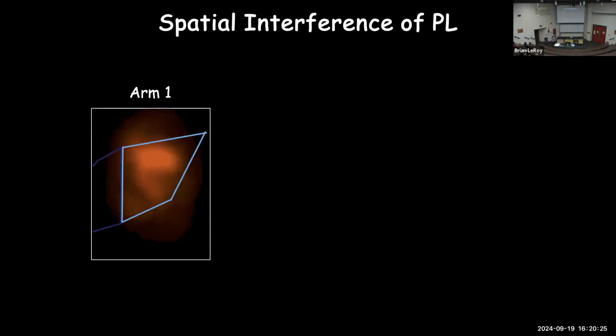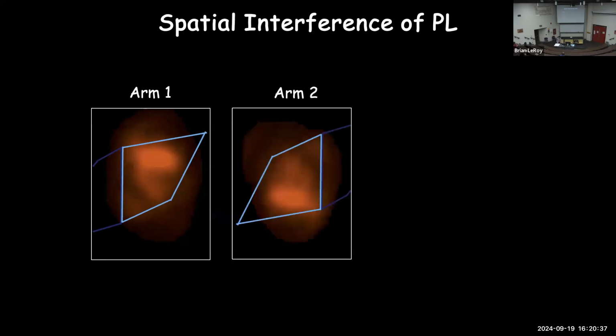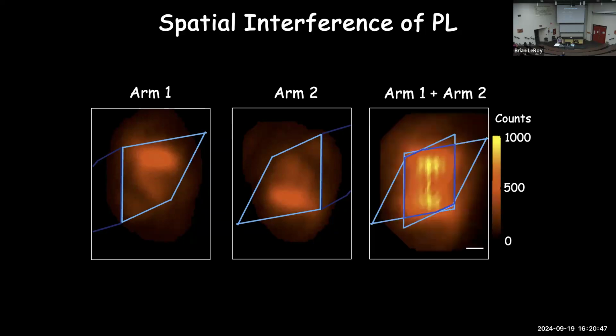And so unfortunately, the colors are very muted here. Hopefully, something will show through here. But this is basically a little red dot here. That's the photoluminescence coming from this side of the sample in one arm. In the second arm, I take this sample, I rotate 180 degrees. Now you see the emission is down here. So these two are like this. And then I take them and I put them on top of each other.